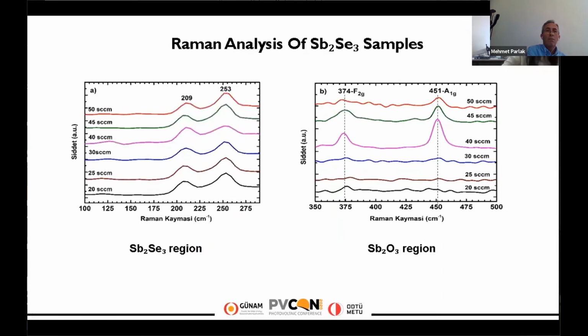Yes, Raman analysis. XRD analysis is not enough by itself. Raman analysis results should support the XRD analysis. Here we see 2 graphs. The first one is the antimony selenide region. The second one is the oxide phase region, the high frequency region. Raman spectroscopy utilizes vibration peaks of the elements, different from XRD.